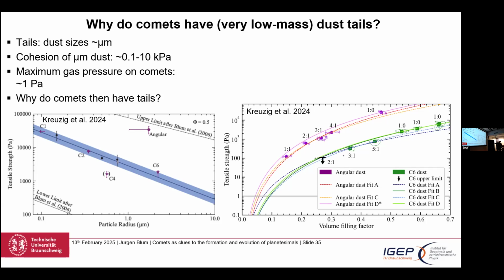So on the order of a kilopascal or more, as a function, this is a strong function of volume filling factor, so 1 minus porosity. So here is the 1 to 10 kilopascal range. If the porosity increases, so filling factor decreases, we're going down, but the smallest we could measure is 100 pascal. So this is the range of cohesions.